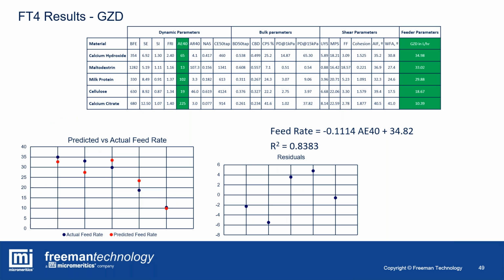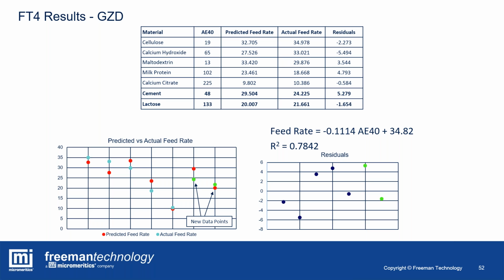When we looked at the actual versus predicted, again, pretty good, with residuals plus or minus 5 or 6 litres per minute, so 10-15%. When we put in the subsequent cement and lactose samples, again, we observed reasonable accuracy with our predicted versus the actual observed retrospectively. What that shows is that the behavior of the materials within the 2 different screw designs is dependent on different attributes of the material. That's probably not surprising when we consider the scales are different. You have twin screws versus single screws and so on.